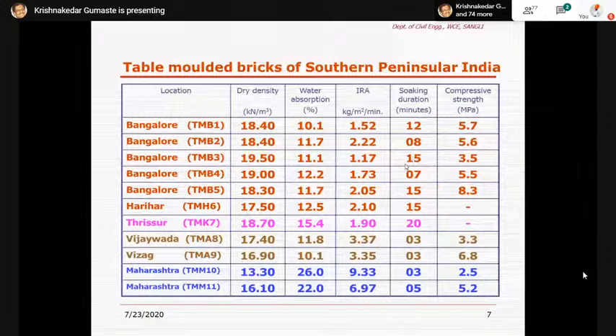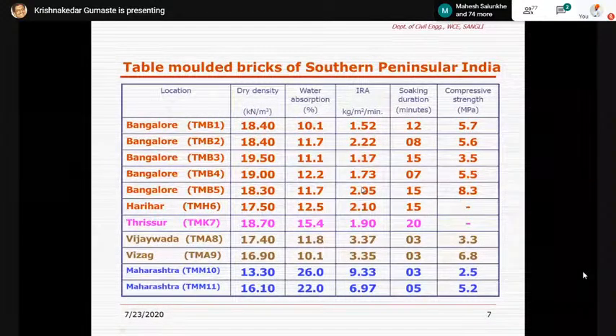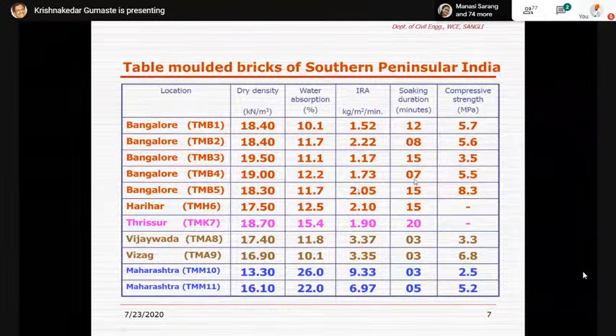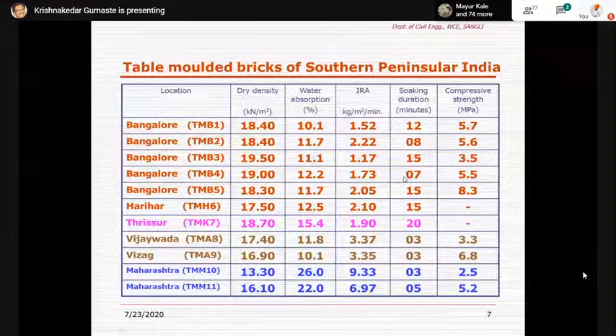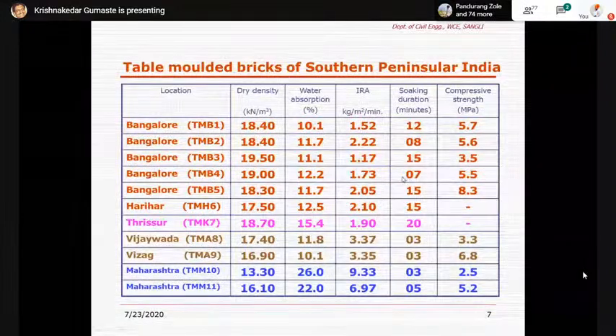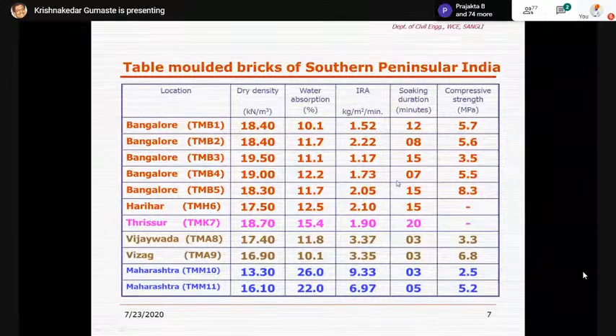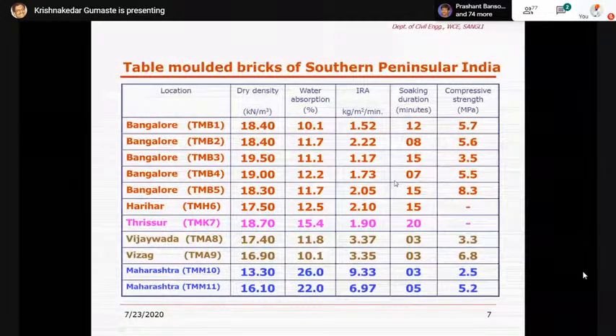Otherwise, if you go to some of the textbooks, when you read, it is said that bricks are to be drenched overnight in a water tank before being used for construction, and nobody talks about what should be the moisture content in the brick during the construction. This is an important property, because there should be no complete absorption of the water from the mortar into the brick, and at the same time it should be partially saturated, because some of the cement paste needs to get into the needle-like pores of the bed surface of the brick, so that they form a needle-like structure.